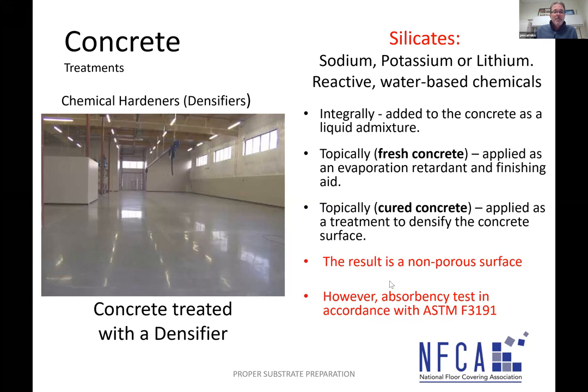The main thing we got to keep in mind here, okay, if a silicate was used, is there's no more residue at the surface of silicate, unreacted silicate, okay, and the surface is clean, but that surface may be non-absorbent and may require a different primer to get a chemical bond to the surface of that concrete. It may require mechanical preparation potentially, okay? You got to check with your manufacturer to see what their recommendations are when dealing with silicate-treated concrete.